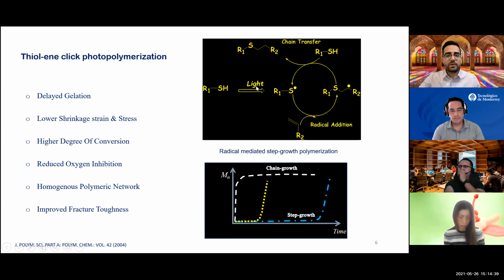Maybe if we are using photopolymerization, we produce a thiol radical, and this thiol radical can interact with the double bonds and then again produce newly generated radicals. Subsequently, these radicals can interact with another functional group, thiol functional groups, and finally it can be done many times and produce polymers. As you can see here, I want to compare the progress of molecular weights for chain growth polymerization, step growth polymerization, and thiol-ene polymerization.